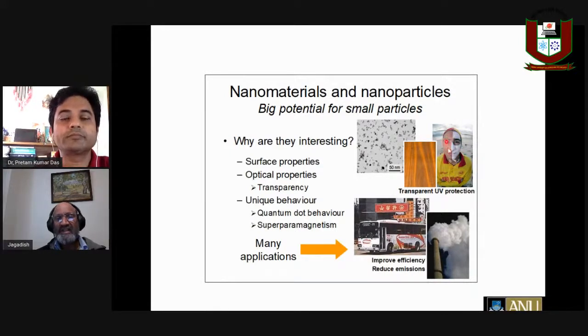But if you use nanoparticles in sunscreens, because nanoparticles are so small, the scattered light is not that much. By controlling the dimensions of these nanoparticles, you can control the band gap of the semiconductor. That means they can absorb only the UV light but allow the visible light to pass through, so you don't even know that this person has applied sunscreen. For the surf lifesaver in Australia, there is a lot of UV radiation and melanoma is a major problem, and we all apply sunscreen when we go out.